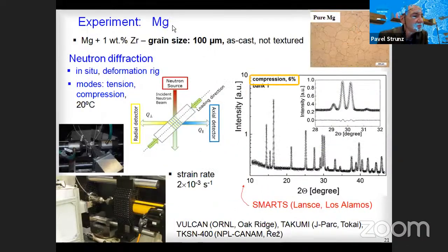I would like to show an experiment on nearly pure magnesium, where we performed a neutron diffraction experiment in situ with a deformation rig on the beam in two modes, in tension and compression at room temperature. One of the measured diffractograms is shown here. Here it is for compression, 6% straining, and it was done at SMARTS.